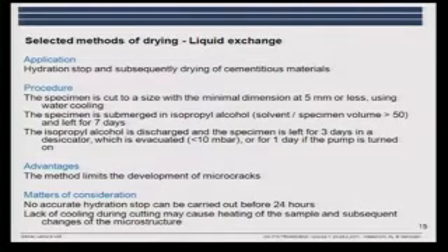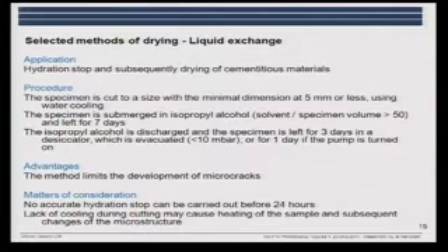So the method can be used both to stop hydration, which you may want, and to dry the sample. You can stop the hydration relatively rapidly, but if the sample is younger than 1 day, you should use another method, freeze drying. So the sample is cut into thin slices, 5 millimeters or less, and then you place it in alcohol, and you need an amount of alcohol 50 times more than the water in the pores. And then after some days, you take the sample and evacuate the alcohol, and then you can store them. Of course, again, when you're storing your sample, you need to store it in a CO2-free atmosphere.